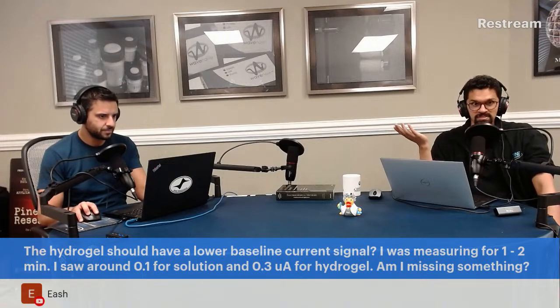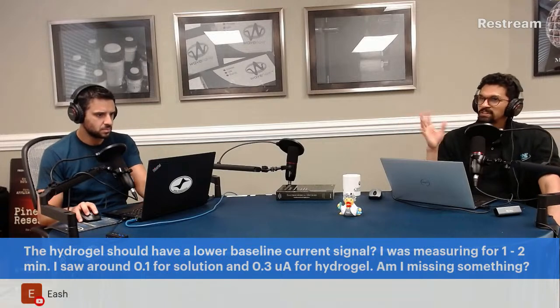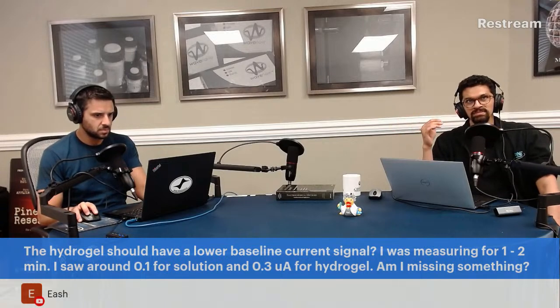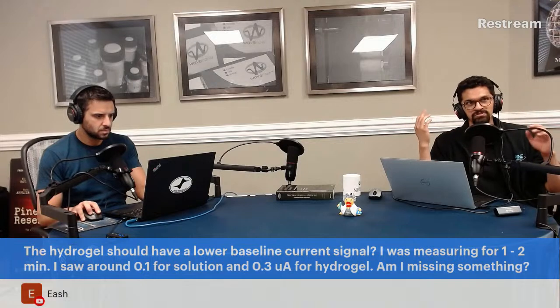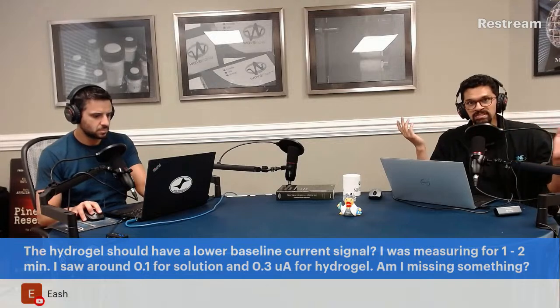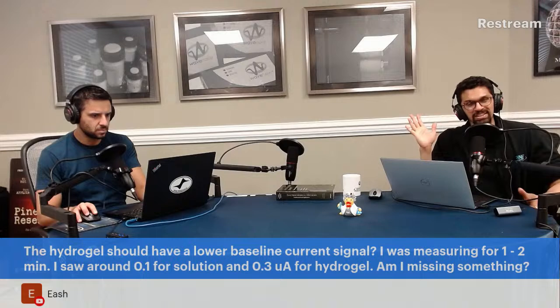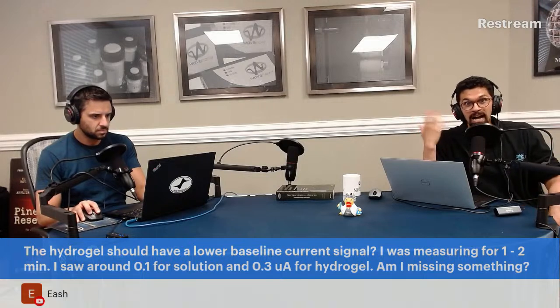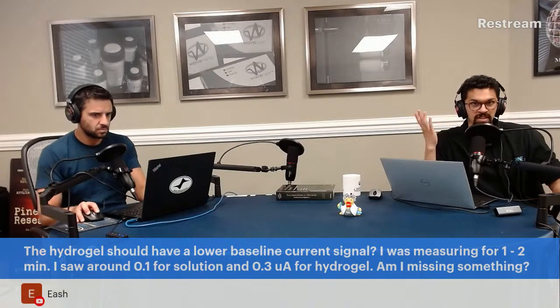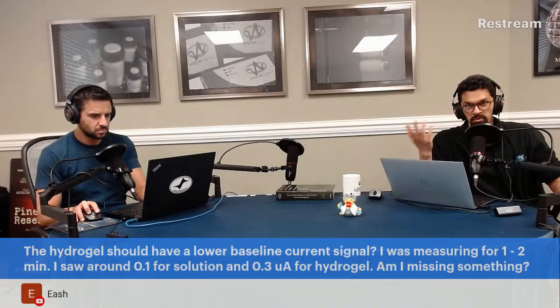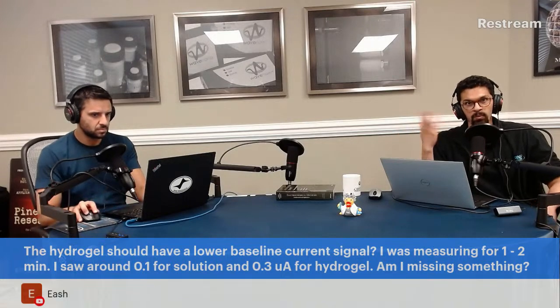So that's what's happening. Here's another question: are hydrogels, because as you said, the resistance can increase. I am curious about the consistency of a hydrogel, like how conductive it is, because this is another one of those weird things in electrochemistry where if the conductivity changes, it has a twofold effect. If you change the concentration of the supporting electrolyte, the effect is twofold. It changes both resistance and capacitance simultaneously. It's not one or the other.